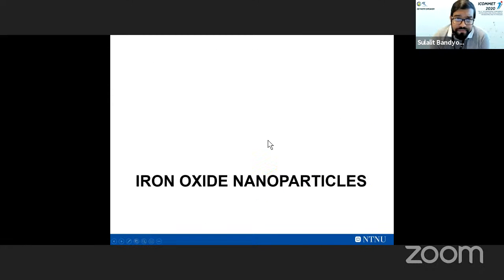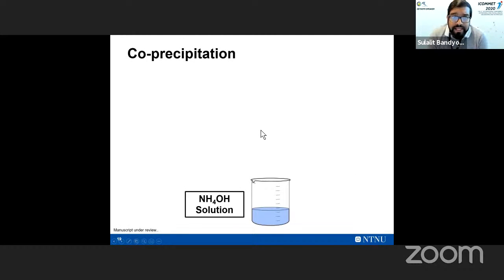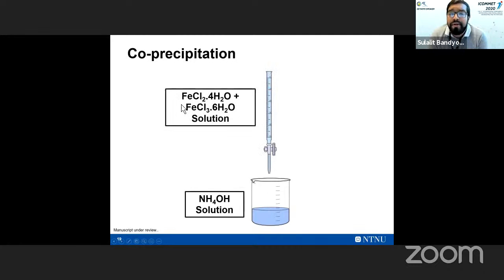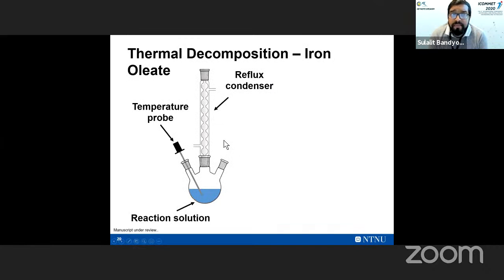We move on to iron oxide nanoparticles, where I would show you two methods. The first is co-precipitation, where you prepare a basic solution into which you drop a mixture of iron salts, Fe2+ and Fe3+, and that results in the formation of magnetite nanoparticles. Another method that we very much use is thermal decomposition. This is the first one, where you use iron oleate. You put it inside a reactor with a reflux condenser and a finely controlled temperature.